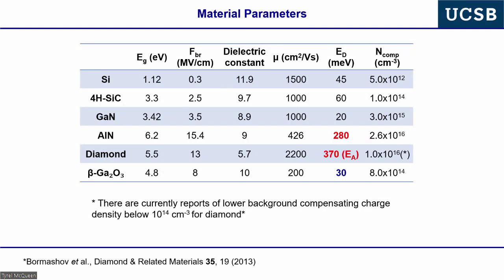A couple of years ago he spent all of his DOE supercomputer budget to calculate, and he said all the donors are hydrogenic in gallium oxide, and I don't know what you're measuring. And because of the dielectric constant, you notice these numbers, like here and here, are quite similar because the effective masses are a little bit higher in gallium oxide than GaN, and the dielectric constants are about the same. Everything's about 10. So very often you get this number that's on the order of 20 to 30 meV for hydrogenic dopants. Okay. And for sure, one of the two sites is hydrogenic, but we don't know which one. And DFT's been unable to resolve it because it's not within the energy resolution of the technique, basically.